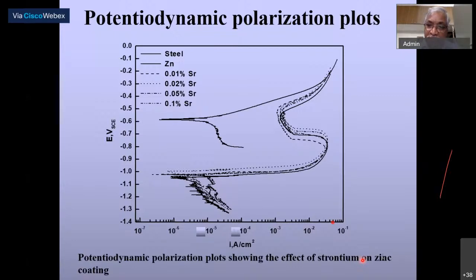So you can also use a simple law of mixture. If the particulate does not corrode at all, for example, or it corrodes less than the matrix, or it is totally inert, then the law of mixture can apply. But the interface between the particulate and the matrix may have some segregation. That may depend upon the energy of the particle. So there is a possibility that it can vary.